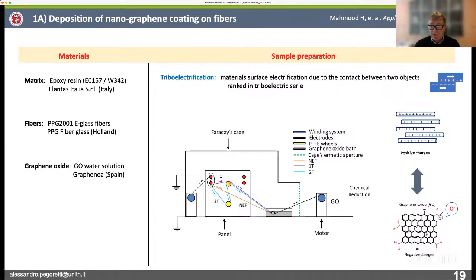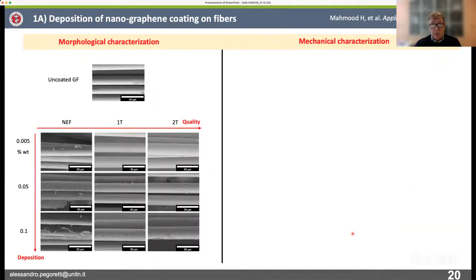In this case, we use Teflon rollers on which the glass fibers were rubbed. At the end, you get a positively charged fiber, and if you have a bath, like in this case, containing negatively charged graphene oxide, you can obtain a coating on the fibers by a very simple technique. Here you can see some pictures of the coating we reached, with different percentages of graphene oxide in the solution, and also different intensity of the rubbing against the Teflon rollers.